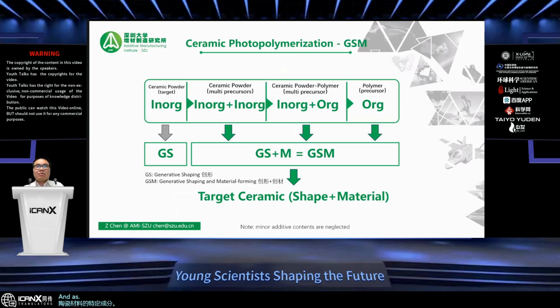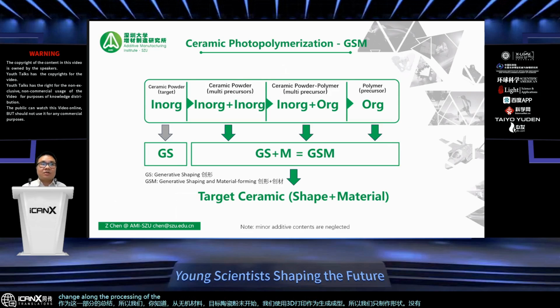And as a summary for this part, starting from inorganic material, the targeting ceramic powder, we use 3D printing as a generative shaping. So we only make shape. There's no change along the processing on the material side, starting from slurry, and then doing 3D printing. There will be sintering. So there's almost zero difference for the powder. There's no change for the powder, but we propose a GSM method.